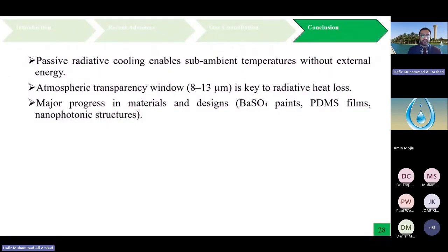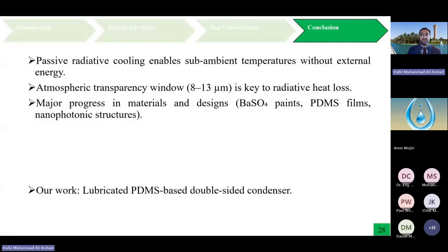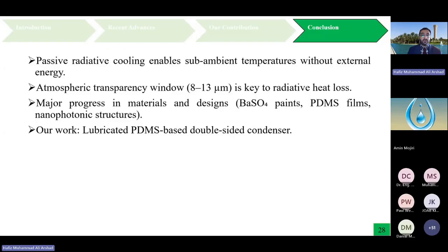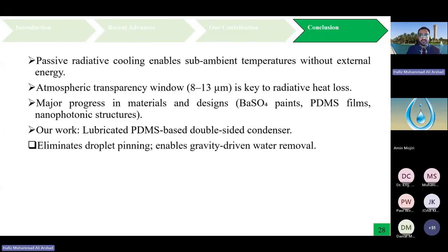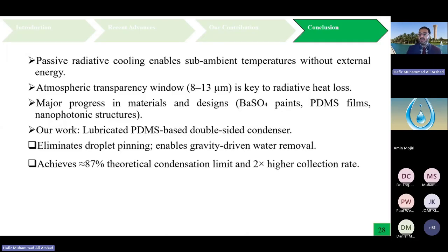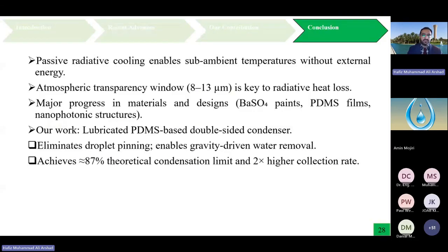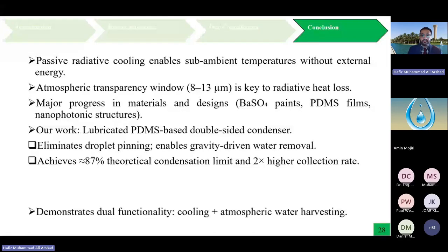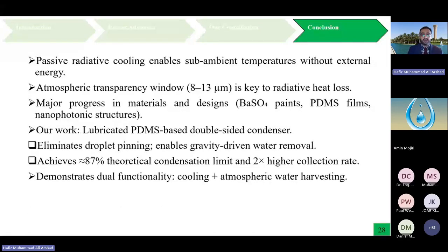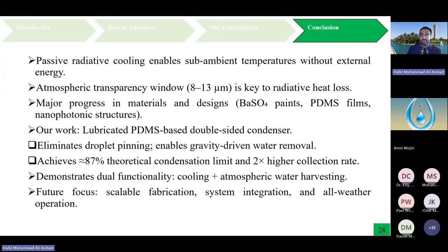The work we did showed that lubricated PDMS-based double-sided condensers were able to eliminate droplet pinning, enable gravity-driven water removal, and also achieved 87% theoretical condensation limit, which was almost double the collection rate. So it demonstrates dual functionality. For example, we can get cooling, which is nowadays used for building cooling, plus atmospheric water harvesting. The future focus should be on scalable fabrication and system integration with some active technology, and that could be done for all-weather operations.